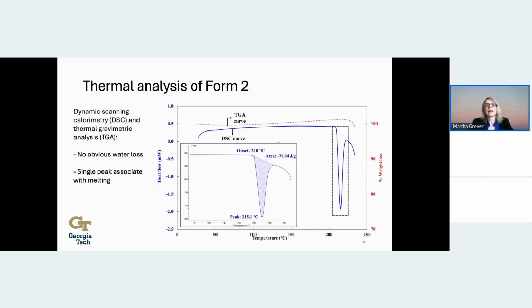And so we performed a thermal analysis of form 2 with DSC and TGA. And we were not able to really discern a trend in the weight loss. There is some upward movement, actually, in the apparent measured weight loss. So that was kind of curious, but we were really not able to observe obvious weight loss. Also, we understood that there really wasn't water available, though we could have had acetonitrile incorporated in the crystal. So anyway, we did not observe any particular mass loss, but it was a little bit inconclusive due to it going up as well, I would say.